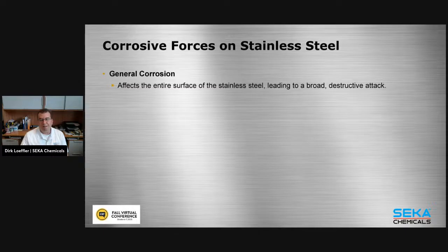General corrosion, we see this very rarely. I mean, if you're in a coastal area and you have stainless steel outside, you might see this over time. This is essentially where the entire surface gets attacked evenly, leading to a broad, usually very destructive attack where the stainless steel will literally fail and large pieces will be failing and looking like the typical rust that we see from iron normally.